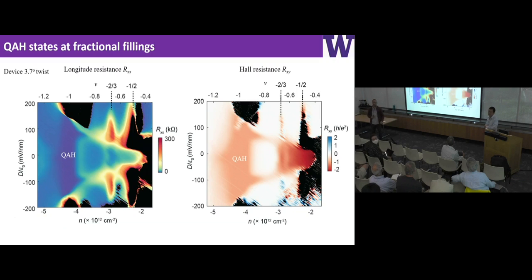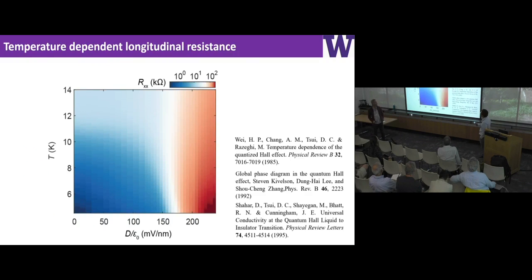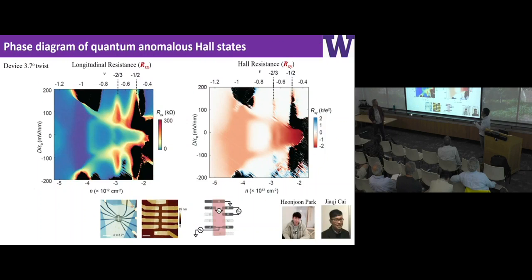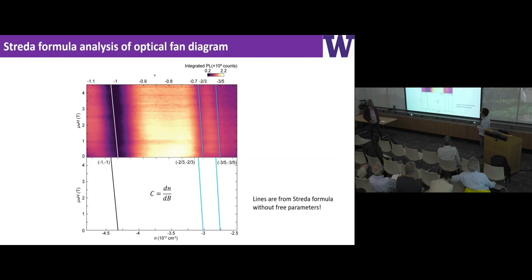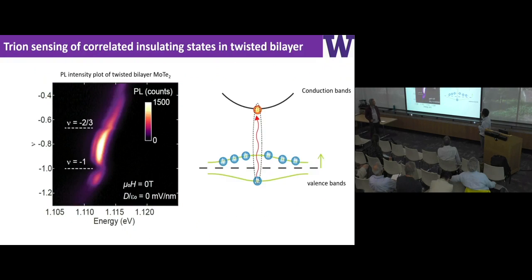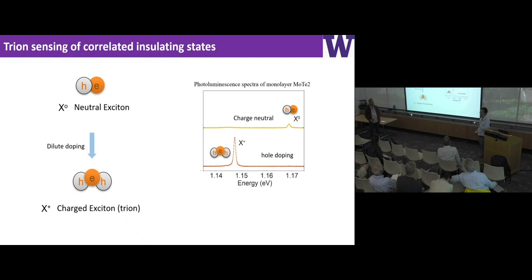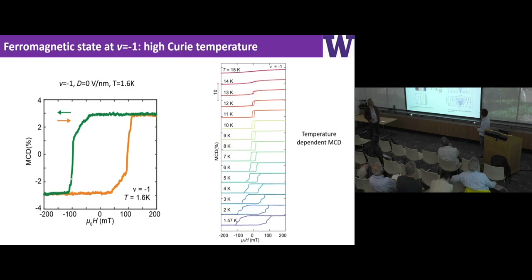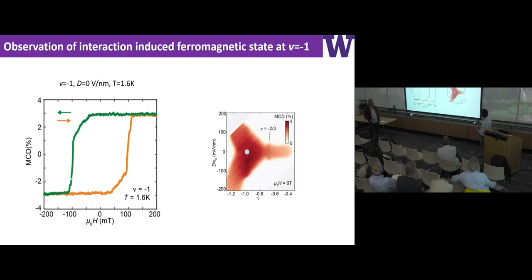Another feature in the MCD is that when you get past -1 filling and go further, this feature seems to disperse and go to finite displacement. Do you know what that is? We explained these ferromagnetic states in our first paper. It's also an anomalous Hall metal regime because you dope it into the metallic regime. These are a ferromagnetic metal phase. That's the simple answer. But why finite displacement?